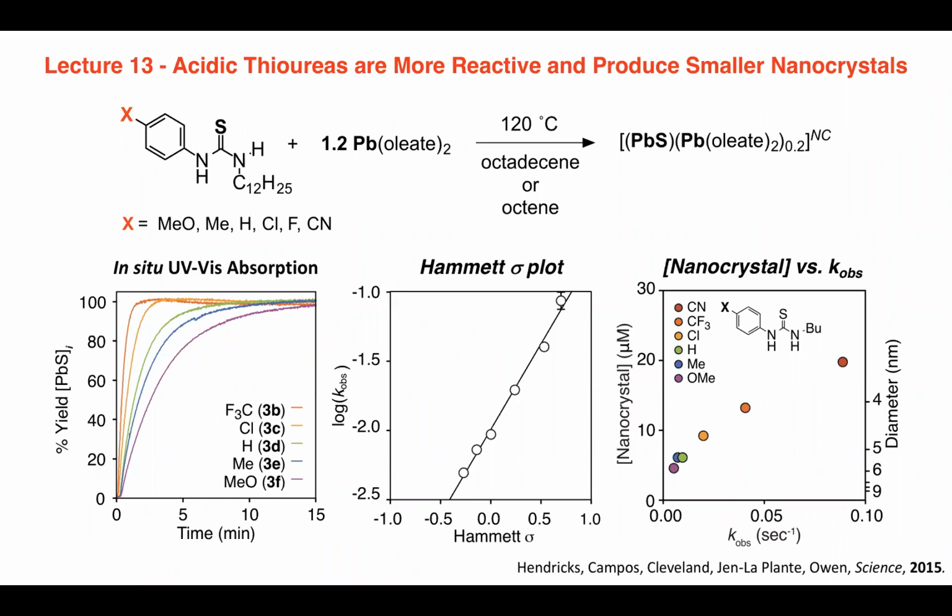So there's all this nucleation growth stuff happening. All you see is the decomposition of this thing, because decomposition is the slow step in this process, all the other steps happen fast relative to that. So you can then fit these curves, pull out rate constants, and those rate constants are related to this breakdown. If you're familiar with Hammett plots, which you ought to be, here's a Hammett plot for these various substituents, and it basically says that electron deficient compounds are faster than electron rich ones. You can use that to speculate about the breakdown mechanism like that.